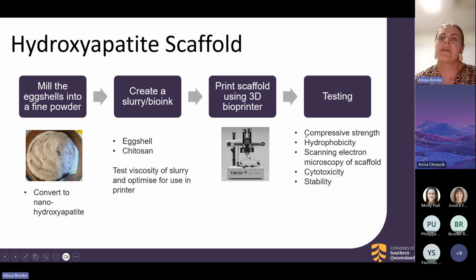So compressive strength is one of the important ones because we want that to be similar to bone. We also need to look at the hydrophobicity. So when you're doing cell culture, if the scaffold or whatever surface you're culturing onto is too hydrophobic, the cells won't actually adhere. So it can't be too hydrophobic. Completing SEM to look at what the scaffolds look like in terms of porosity and do they represent bone. Cytotoxicity, so if these scaffolds kill the cells, that's obviously not going to be useful for this particular research, as well as stability. So knowing how long the scaffolds can actually sit, and then therefore obviously the shelf life of this product.